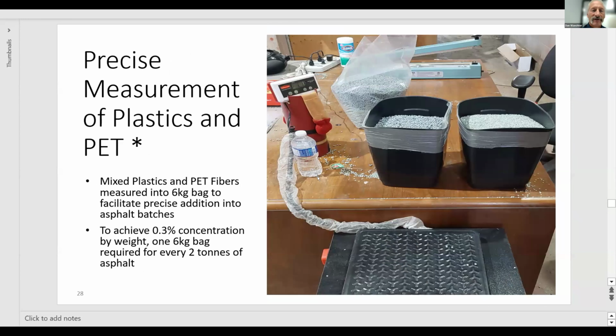Mixed plastics and PET fibers had to be measured into 6 kilogram bags to facilitate precise addition into the asphalt batches. In order to achieve 0.3% concentration by weight, one 6 kilogram bag was required for every 2 tons of asphalt.